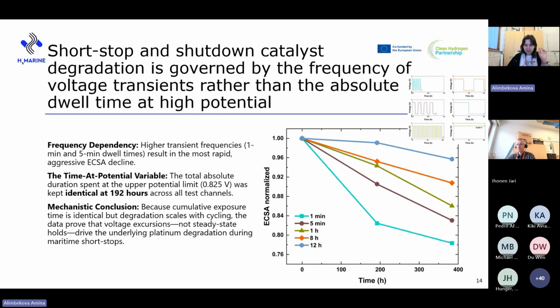Because the absolute time spent at the upper potential limits is the same, it means that the rapid and frequent voltage transitions themselves give the most degradation to the platinum catalyst. This provides the conclusion that under maritime shutdown conditions, the catalyst degradation is also governed by the number of voltage transients rather than the time spent at these high voltages or upper potential limits, because each excursion, each voltage transient, triggers the oxidation reduction cycle that accelerates platinum loss.